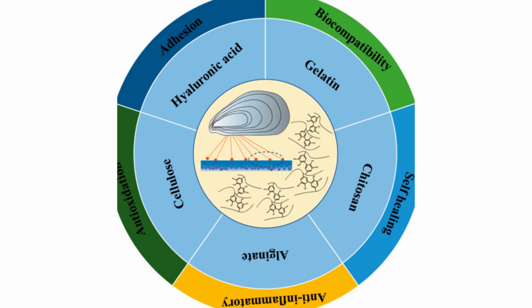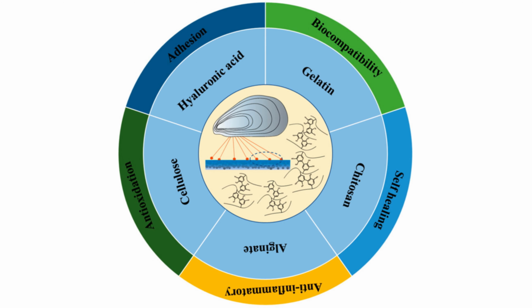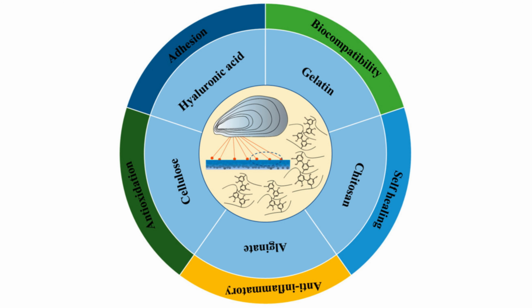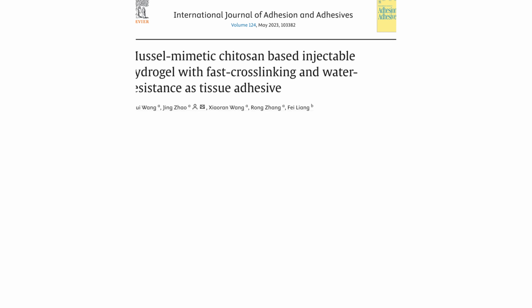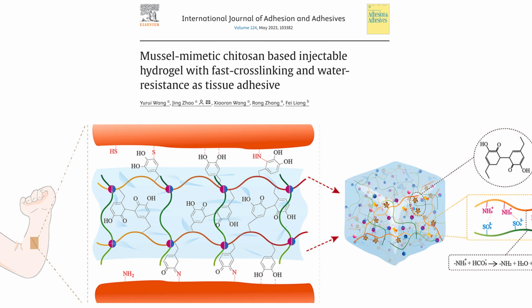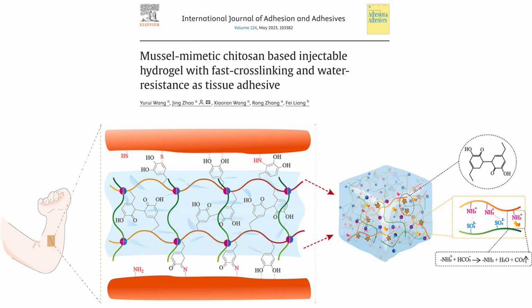Bioadhesives, hydrogels, and functional coatings. Mussel-inspired chitosan hydrogels. Dopamine/catechol-modified chitosan yields fast-gelling, strong, wet adhesive networks for tissue sealing and wound care. Recent reviews map chemistry and clinical-leaning performance: toughness, self-healing, antibacterial. For sustainable materials, these same chemistries translate to wet bonding coatings for paper/bioplastics and anti-fouling layers, replacing petro-epoxies in some uses.